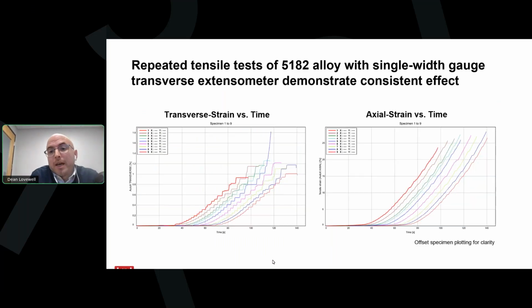And so here's a look again at those same tests. What we're looking at is the contributing axial on the right and transverse on the left strain data for these tests. This really demonstrates the consistent unpredictability of the transverse strain behavior that's directly contributing to the variation in our R value. You'll notice that my plots are all offset so that we can easily see how each test progressed relative to the other tests. This is possible using a simple toggle switch in Blue Hill that I use regularly when I'm reviewing test-to-test data.